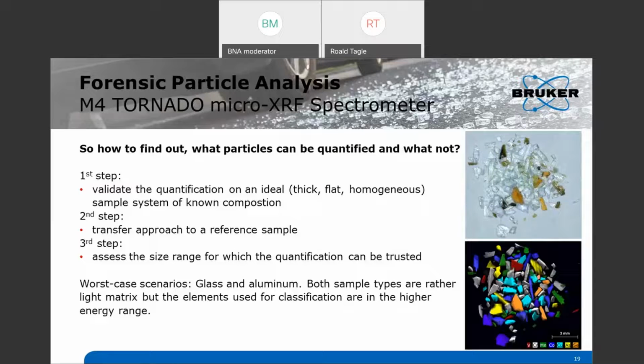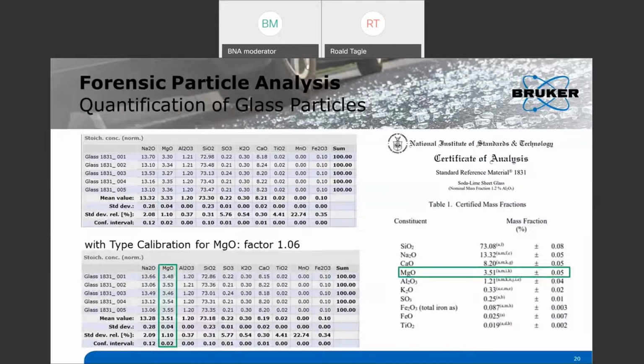So the first step is to validate whether the quantification can be used at all. So you need a standard to verify that it works. Then in a second step, you take a reference sample which you have no problems to destroy, and you produce a lot of tiny glass pieces of different size and assess the size range for which this is possible. This is especially interesting for glass and aluminum particles because those are a pretty light matrix but have heavy elements which are needed to properly characterize the particles.